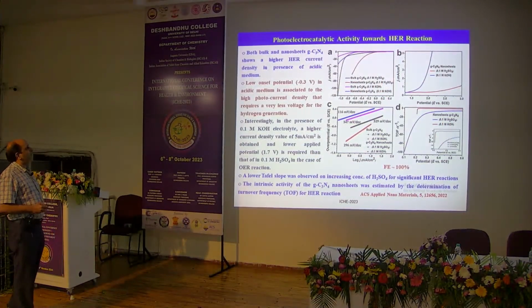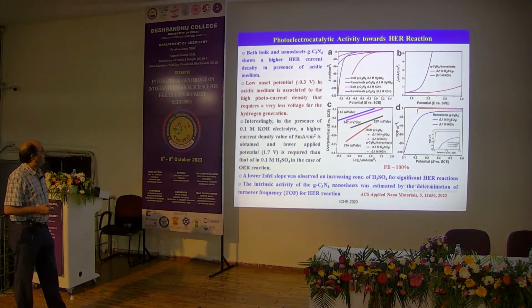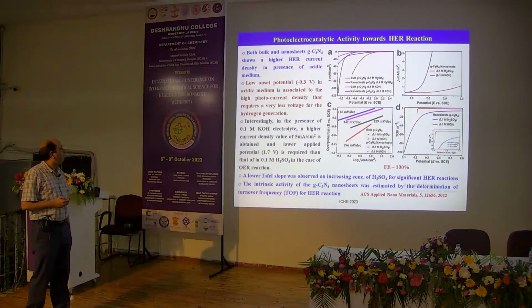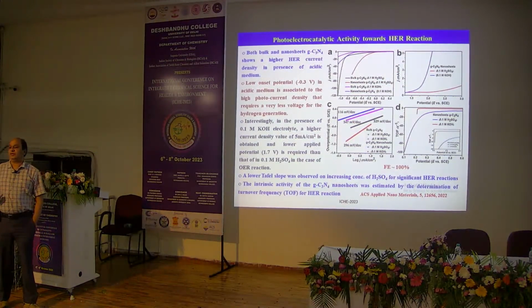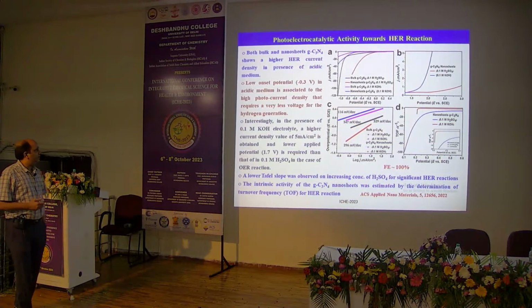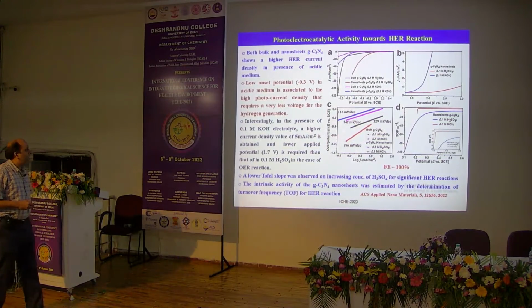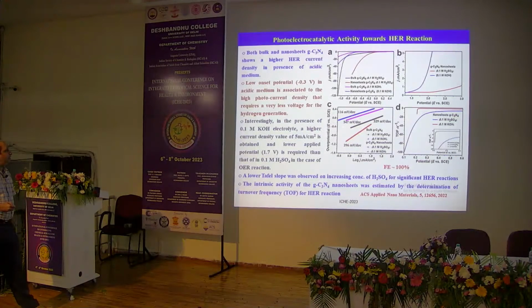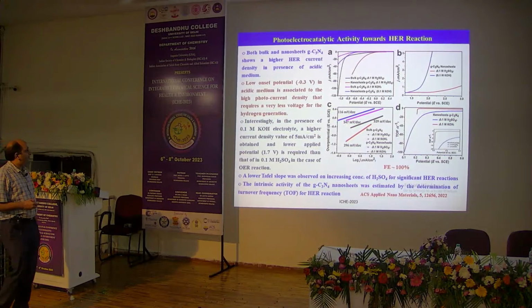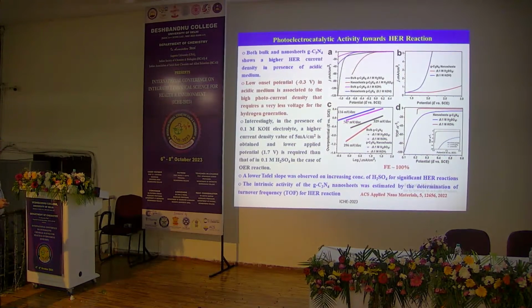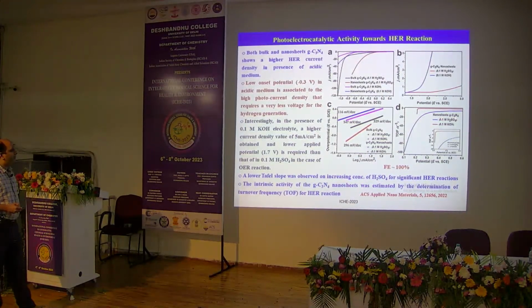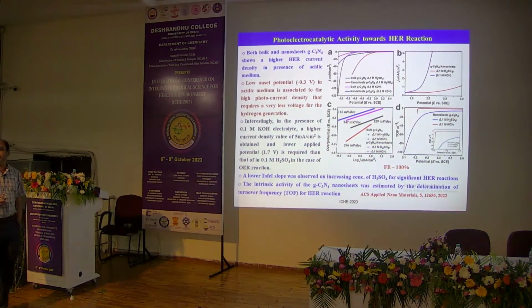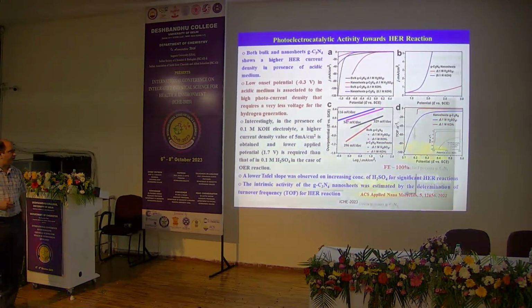So this is the HER plot and this is the OER plot. A low value of the onset potential can lead to a high photocurrent density, which requires less voltage for significant hydrogen generation. And this is the Tafel slope. Here you can see the low value of the overpotential, which shows significant HER reaction, and this is the turnover frequency plot, which is used to determine the intrinsic activity of the graphitic carbon nitride nanosheets.